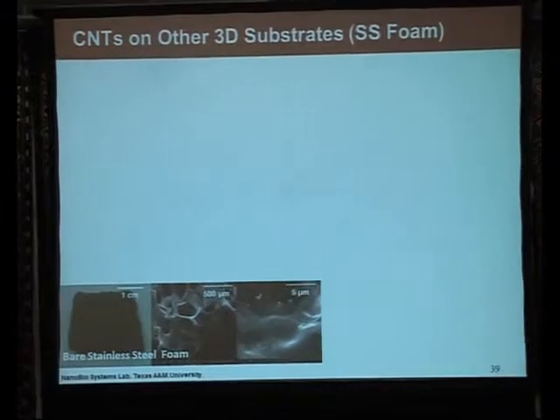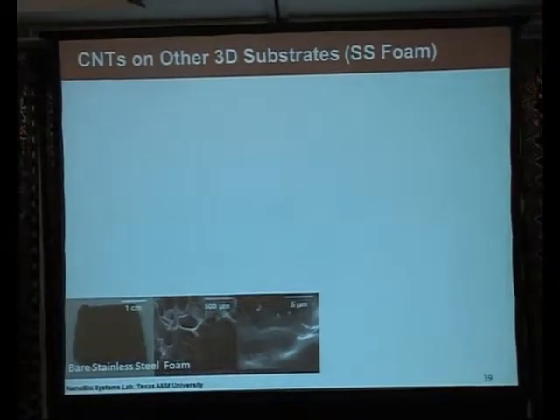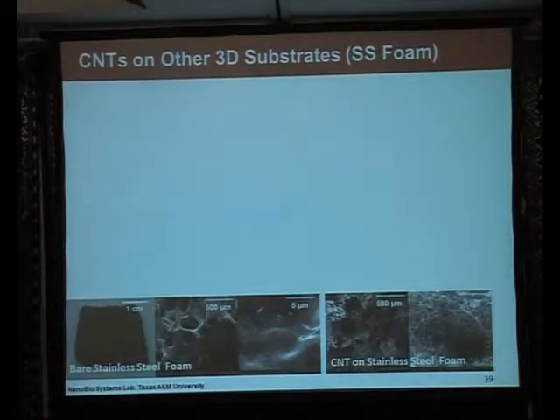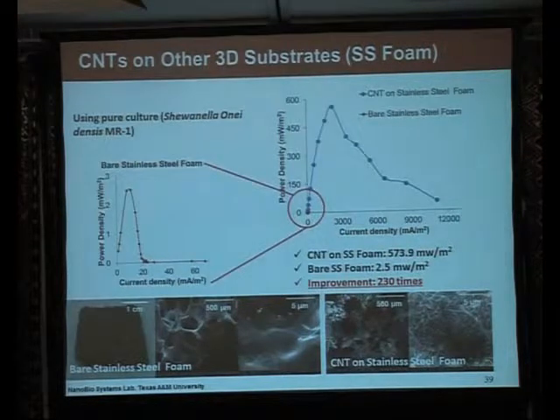So these are the electrodes before the MFC and after the MFC, where you see biofilm formation. We have also applied this strategy to growing carbon nanotubes on other substrates, such as stainless steel foam. As you can see here, before carbon nanotubes and after carbon nanotubes, this is again a significant improvement in power output compared to a bare electrode.